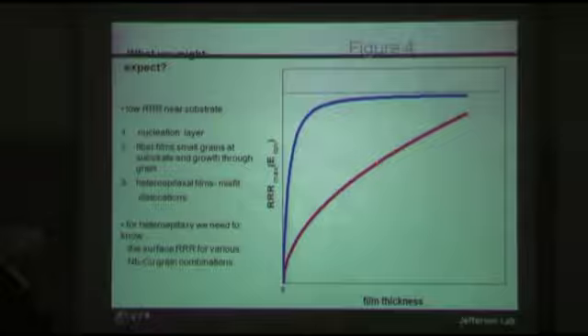We might expect the RRR value through the film from substrate to the final thickness to look like the red and blue curves in the graph shown here. The blue curve represents a defect density saturating fairly quickly with film thickness, as opposed to the red curve. And the asymptotic value of the blue curve represents the best value obtainable for that particular ion energy. And for different ion energies, you would expect a family of similar curves with different asymptotic values of RRR.